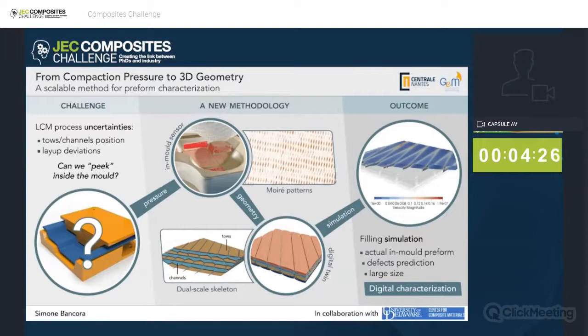But here lies the challenge. Once the mold is closed, it becomes difficult to track the position of layers, yarns, and eventual deviations from the layup. This is why it's hard to predict properties of a dry preform and run filling simulations that might help to predict defects. It is also why, in my experience, working together with more than one company, I found that rather than trying to simulate something so unpredictable, we sometimes rely on trial and error and deal with defects as they come.